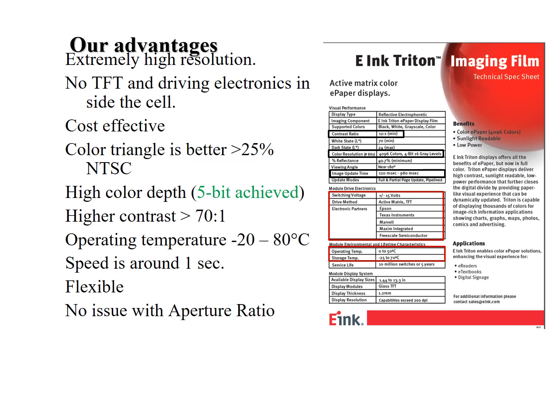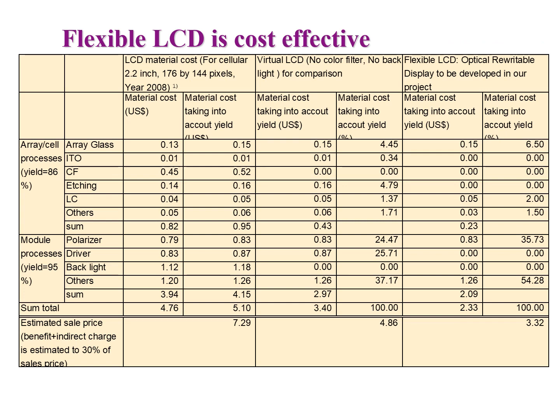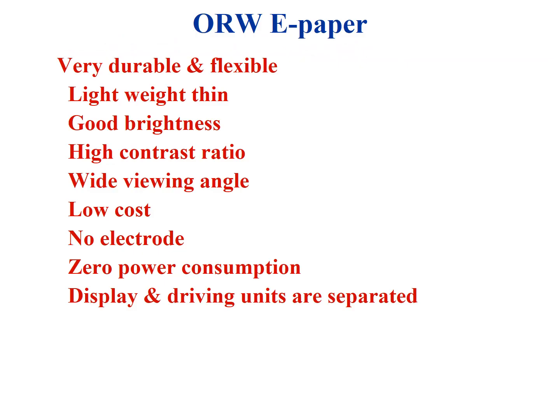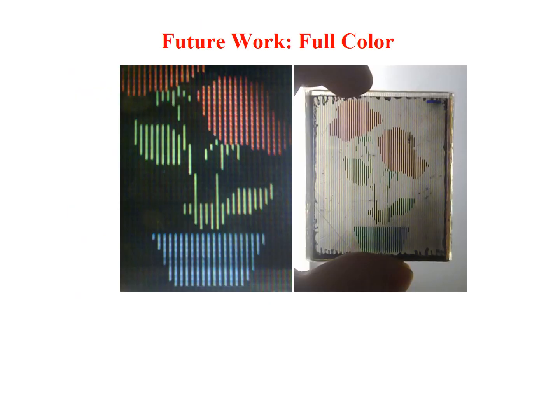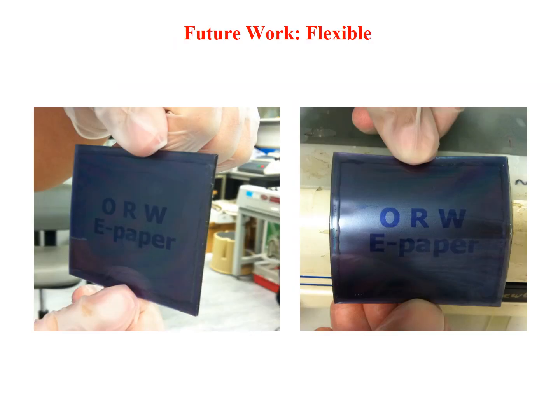If you compare e-paper based on photoaligned azo-dye layers with e-paper using, for instance, the company Toppan, we can tell you that our e-paper is cost-effective because there is no TFT drive electronics. It has a color triangle, excellent, much better than electronic ink. 5 bits of gray levels are achieved, high contrast ratio, and a very wide temperature range, and it can also be used on flexible substrates. If you compare the price of our optically writable paper to the cheapest liquid crystal display, because we have no current conducting layer and no drivers, it is several times less. So we have a very durable and flexible display, lightweight, high quality, wide viewing angles, and zero power consumption. Now we are working on color e-paper and flexible e-paper, and hope we will show you our results soon.